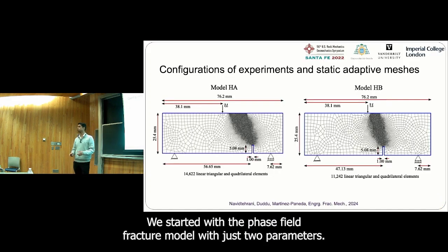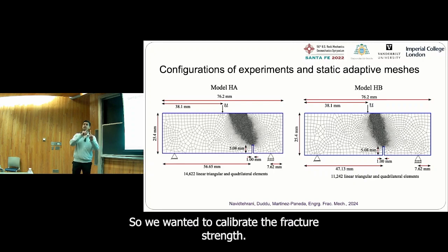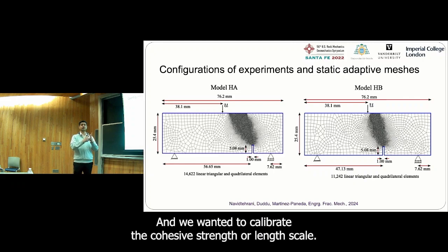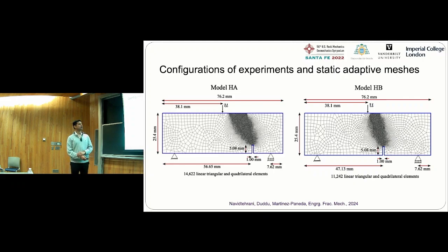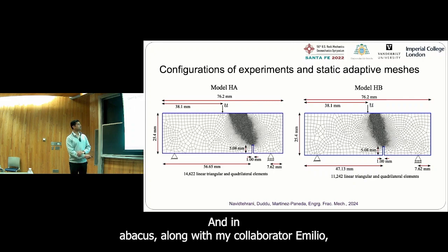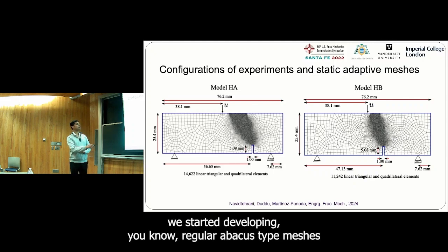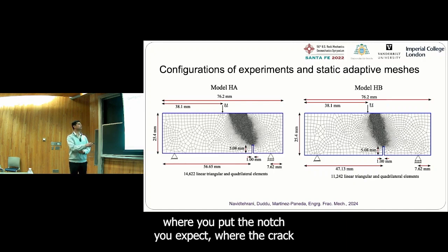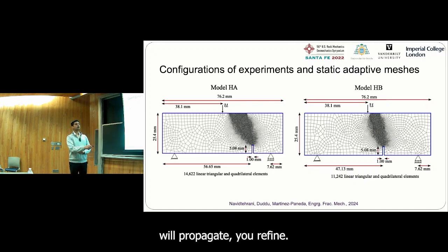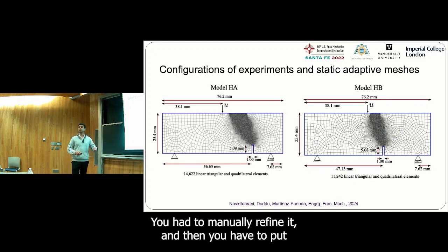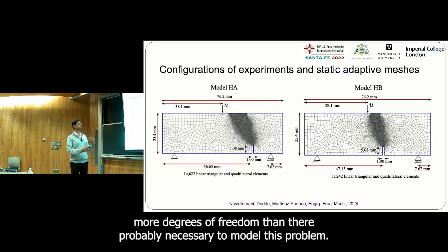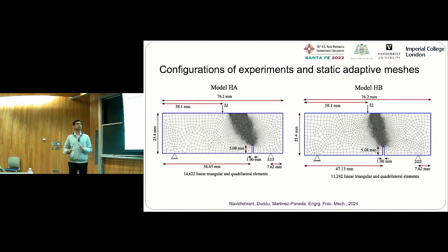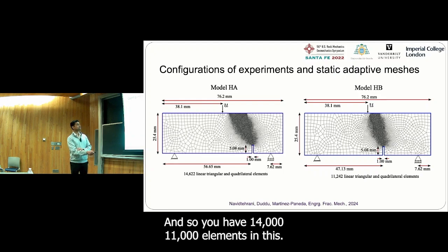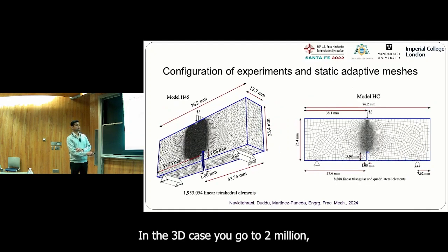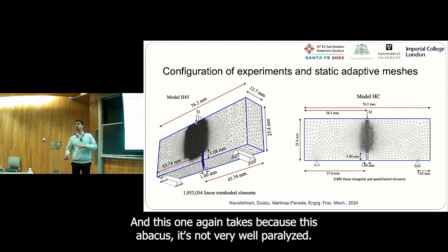We started with the phase field fracture model with just 2 parameters, right? So we wanted to calibrate the fracture strength, and we wanted to calibrate the cohesive strength or length scale. They're dependent. And in Abaqus, along with my collaborator Emilio, we started developing regular Abaqus type meshes where you put the notch, you expect where the crack will propagate, and you refine. But this is cumbersome, right? You have to manually refine it, and then you have to put in more degrees of freedom than are probably necessary to model this problem. So you have 11,000 to 14,000 elements in this. In the 3D case, you go to 2 million tetrahedral elements, which is a lot.